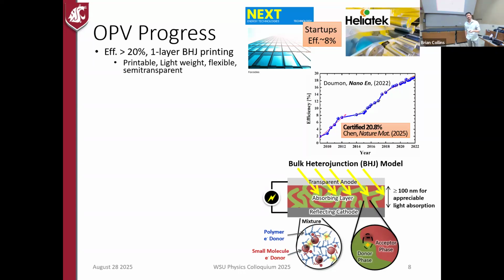But the way that these work, you don't want just two slabs and one junction. You want a huge amount of interface, maybe tens of nanometers apart. And so that's tough to do. So we have this method where you print these things and try to get the thermodynamics to phase separate them at that level, freeze that morphology in place to generate the charges that you need.